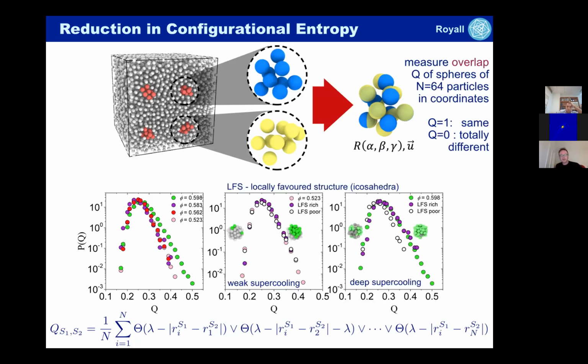Now, it turns out that's also correlated with these local structures. What I'm showing now in these two new graphs, at weak supercooling, all the data falls on top of each other. There's nothing much happening with the local structures. On the right, the white data is not in the local structure and it's got a smaller Q, whereas the purple data is when the particles are in the local structure, and that has the higher Q. So in other words, these local structures are correlated with a drop in the configurational entropy.